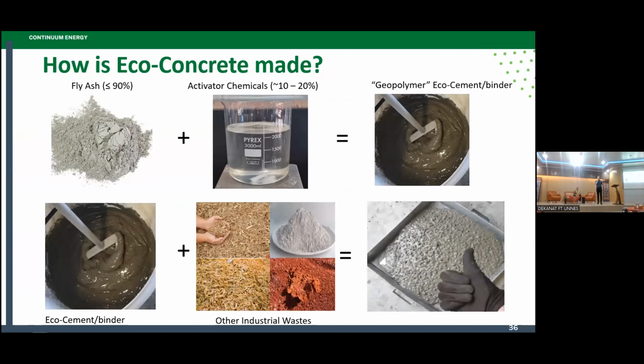We mix it with a small amount of chemicals to make the reaction a bit faster. And from that, we make our eco cement. We can use various waste materials such as coal fly ash, bauxite residue red mud, agricultural waste, rice husk ash, hemp pellets, and we make a cement material that incorporates 90% waste materials and is responsible for 80% less carbon emissions than regular concrete. So again, 80% less for an industry responsible for 8% of the world's emissions.